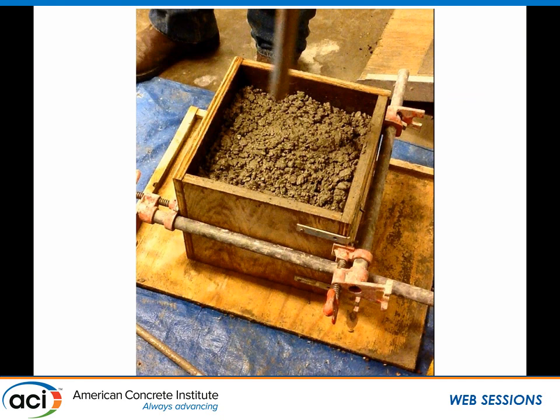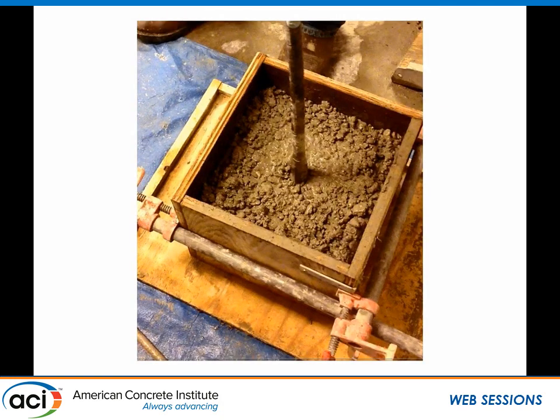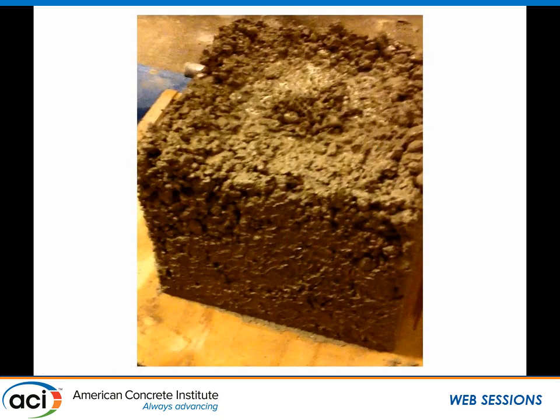We've got our nine and a half inches of unconsolidated concrete. We've got the vibrator going above. Bring the vibrator down, three seconds, and we can see with our own eyes the sphere of influence of the vibrator. It's about here — it's not quite where we want it to be. We want it to be at the edge. When we pull the vibrator out and drop the edges of the forms, there's honeycombing on the sides. This is not what we want — it means it didn't respond well to the vibration.